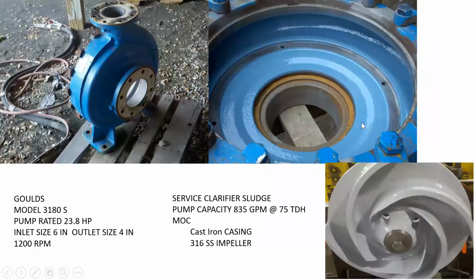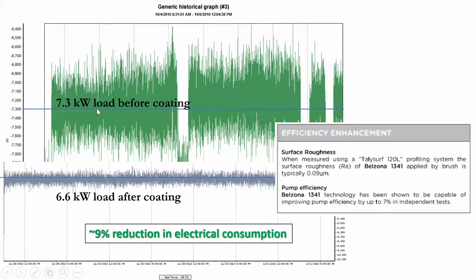And then this is the case history for the efficiency testing that was done. They had a cast iron casing with a 316 stainless steel impeller. Both the casing and the impeller were coated with Belzona 1341. And it showed a 9% reduction in electrical consumption. The reason for this would be the surface roughness of the coating. It's a very smooth coating, so you're reducing friction within your pump. Also, over time, you're not dealing with corrosion that could reduce your pump efficiency as well. So over time, that reduction in electrical consumption is probably going to be even better.